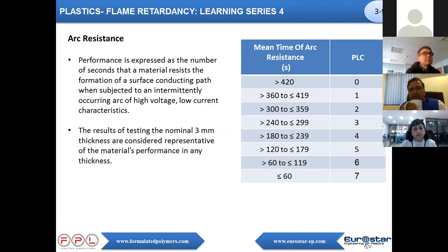And depending on the results, of course, you have different performance levels. So if the time is below 1 minute, then the material is really not suitable for E&E application. And if it's above many minutes, then you can really use it for applications in E&E. So this was, let's say, most of what you would call the short-term properties at UL. In the next presentation, I think there is a table that summarizes that. And depending on the different levels, you have the right or not the right to use the material for an electrical application if you have to apply the UL standard.